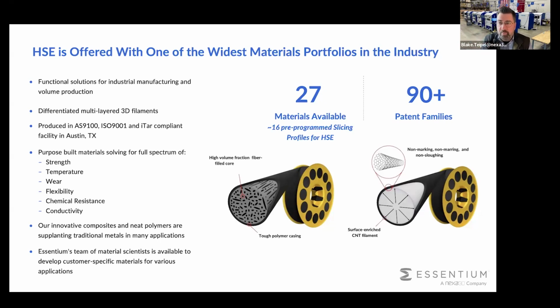The reason why that matters is because you can get high spec materials at low prices, right? Our prices are not crazy. You'll see that if you want, we can buy materials through our web shop. But making a multi-layered filament allows you to do a variety of important things. So I remember I told you earlier, I would tell you the secret behind our HTN CF25. Well, the secret is it's a multi-layered filament. So we put that high spec, highly packed 25% carbon fiber core, and we put a thin candy coating around the outside of neat polyamide, polyphthalamide material, the same chemistry, just neat resin.